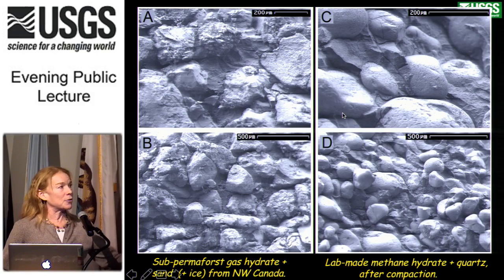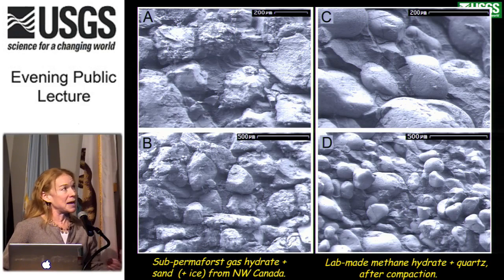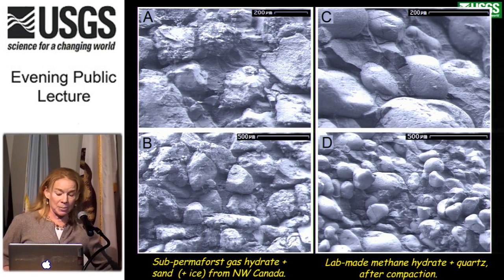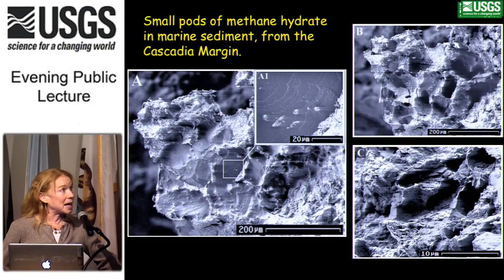So the samples recovered from nature also incorporate some ice in them, ice that formed during the recovery of the sample. The samples that we make are the pure methane hydrate, and that's what we test so that we don't have that ice contaminant phase, which very often changes the properties. Let's look at some marine hydrates.